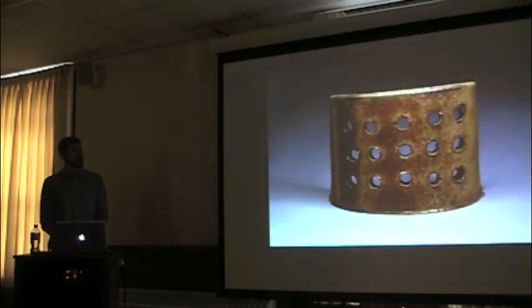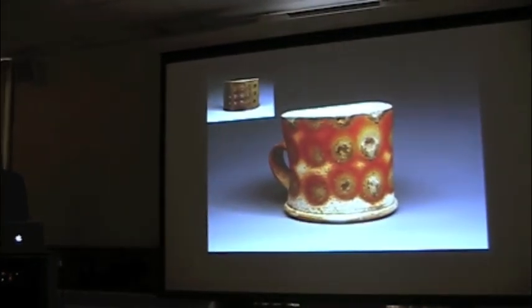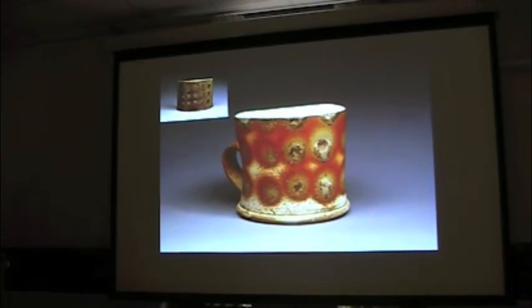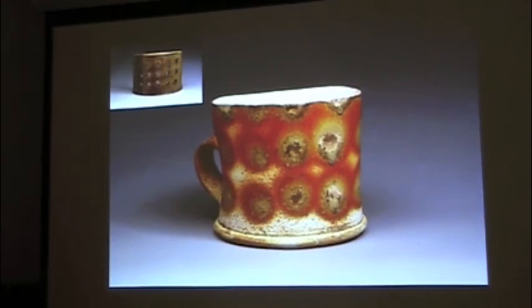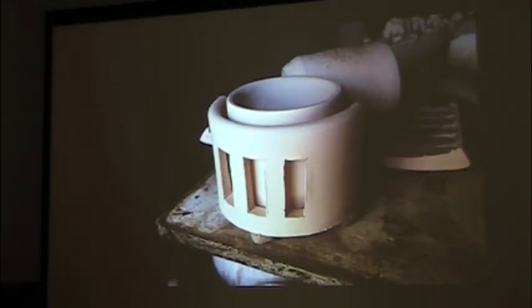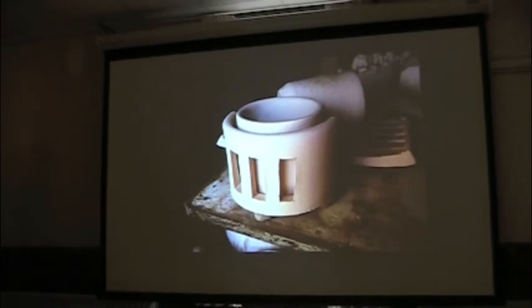I came up with an idea I termed a flame deflector: a cylinder cut in half with holes cut in it, used in the kiln to control how the flame hit the work. As opposed to having a really organic, loose abstract mark-making process, now there's a lot of intention to how the flame is hitting the surface — it's controllable. I'm getting a slightly blurred but recognizable mark — a bunch of dots. This is an image of loading in the kiln to show how that works. But then I was frustrated: what are these flame deflectors? Because clay shrinks, I couldn't reuse them — they became a one-time-use thing and were just ending up in the dumpster.